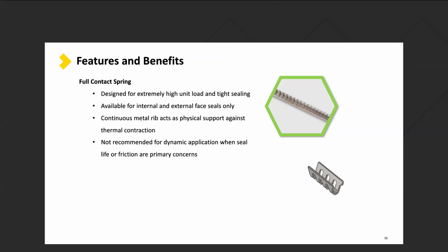The downside of this spring, unfortunately, is it can only be used for face seal applications, internal or external face seals. And the reason for that is you can't stretch or compress the continuous rib if it's configured radially. It would have to either stretch, tear, or it would ripple and bind up if you tried to use this spring in a radial application. So face seal only. The other downside to this spring is that as good as it is, once it's installed in the seal and in the application, it's very difficult to get it into that position.